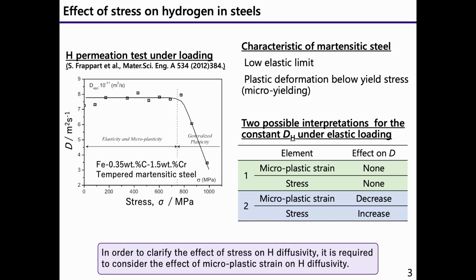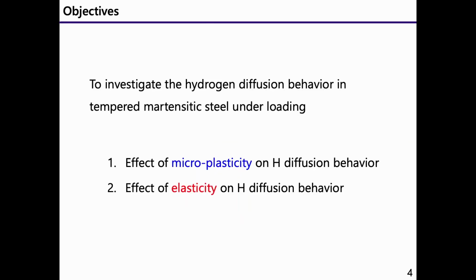Another interpretation is that microplastic strain may decrease hydrogen diffusivity as general plastic strain does, and stress may increase hydrogen diffusivity, and these effects cancel, and hydrogen diffusivity under elastic loading is constant. In order to clarify the real effect of stress on hydrogen diffusivity, it is required to consider or remove the effect of microplastic strain on hydrogen diffusivity. Therefore, in this study, we investigated the hydrogen diffusion behavior in tempered martensitic steel under loading, and the effects of microplasticity and elasticity on hydrogen diffusion behavior.